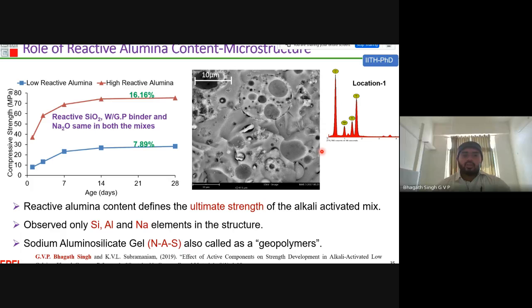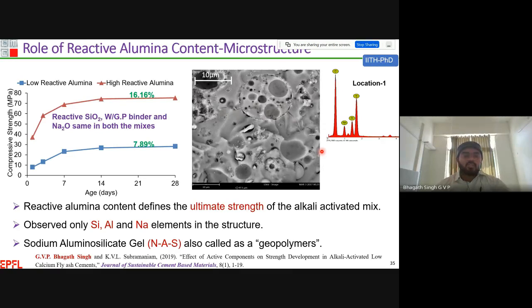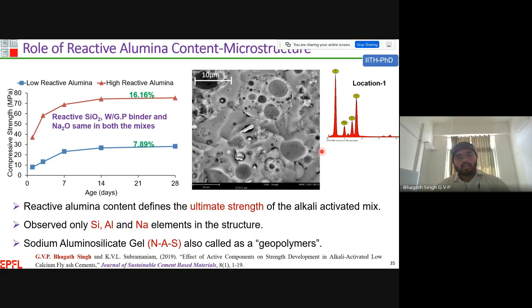And coming to the role of reactive alumina content as well as microstructure. So far I'm talking about the silicates and all those things. Now, what is the role of reactive alumina content? For the reactive alumina, we have to completely rely on the fly ash source, because we can't add the reactive alumina externally. Why? Because it is a very expensive element, and we have to think from an economical point of view, and that is the reason we don't want to use reactive alumina externally. And also, this research is still going on for this particular component, and we don't know which type of format is available in the fly ash, and also the real time locality,